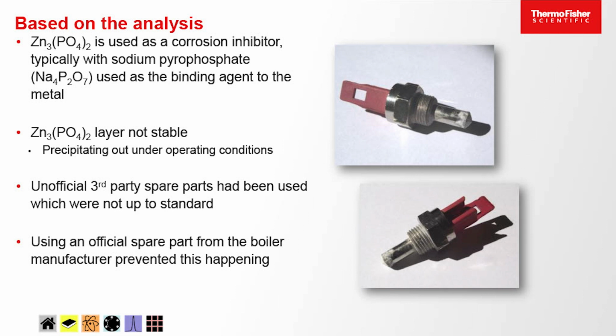The coating wasn't being applied correctly. It wasn't being fixed to the surface of the sensor. And so that was causing the breakdown and the release of this compound in the water system, and it was just precipitating out on the surface of the sensor and causing the failure. Once it was swapped to using an official spare part where this zinc phosphate coating was applied correctly, then the temperature sensor worked perfectly, and my parents were able to enjoy their shower. So that was the thing.